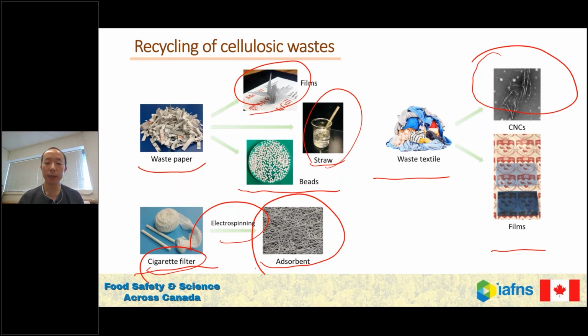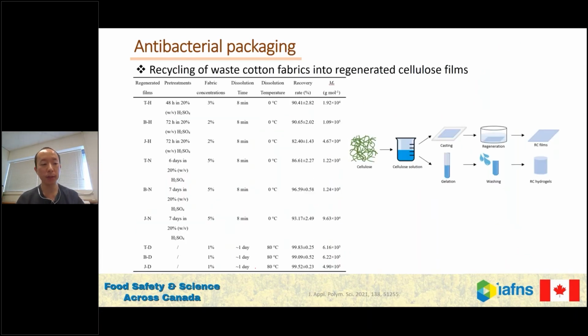And today I would like to talk about some work related to antibacterial materials. We have 3 different strategies to build up these antibacterial packaging materials. The first strategy is, as we mentioned, we can dissolve cellulose, and then convert it into a film or a hydrogel structure. We dissolve cellulose and then cast it or spread it on a smooth surface, and then we can neutralize the solution, so it will come back from the solution to the film structure. We can use a t-shirt, a bed sheet, or jeans, dissolve them, and get cellulose films.